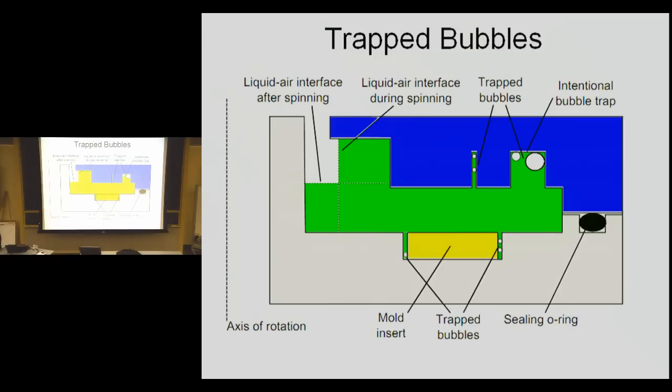So barring that growth, is it that the big ones get bigger and the small ones get smaller? This Ostwald ripening type thing? For the sizes that would have been getting smaller, you're absolutely right. We didn't detect those. We couldn't see those at the scale we were looking at. I agree 100% that there could have been very small bubbles that went right into solution, and they did so very quickly. But they would have still been exposed to the same supersaturation fraction that the larger growing bubbles were experiencing. Again, we're interested in figuring out what that supersaturation fraction was, based on the bubbles that we could see grow. Okay.